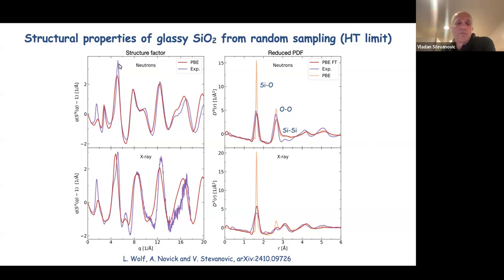So in red is our result, in purple is experiments. If you go to directly measured quantities, which is the structure factor, the correspondence between peaks, their positions and their intensities is fairly good. The only exception to that is this first peak. And as we discuss in this paper, this is I think the price we need to pay for small cells.